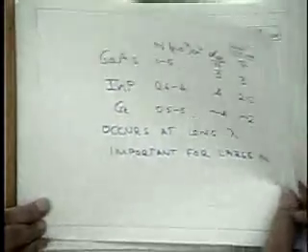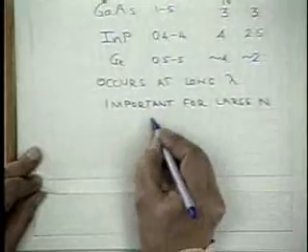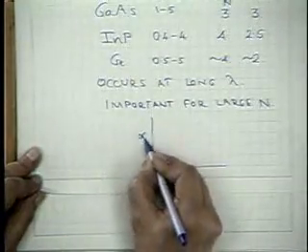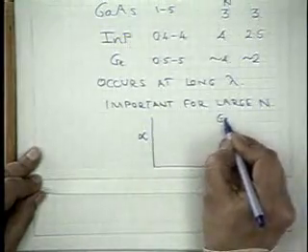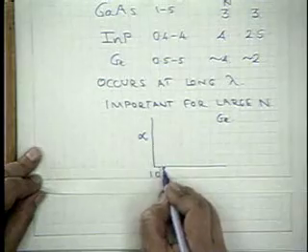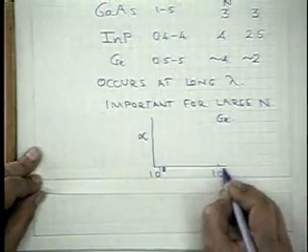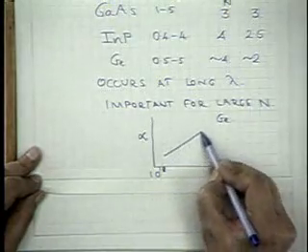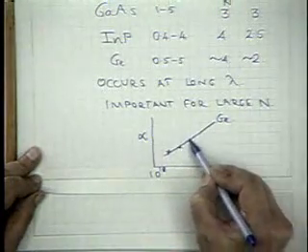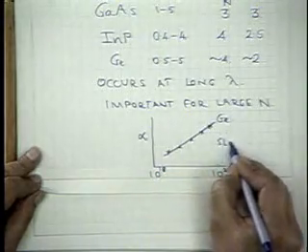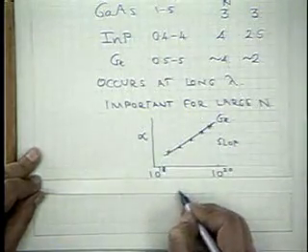Experimentally, one measures alpha. Say for germanium, alpha has been measured as a function of carrier concentration going from, say, 10 to the power 18 to 10 to the power 20, in specimens with different carrier concentrations, and the slope. This is alpha against N.